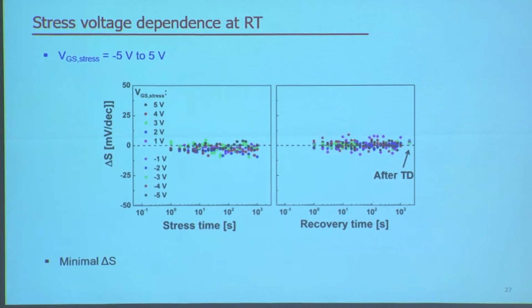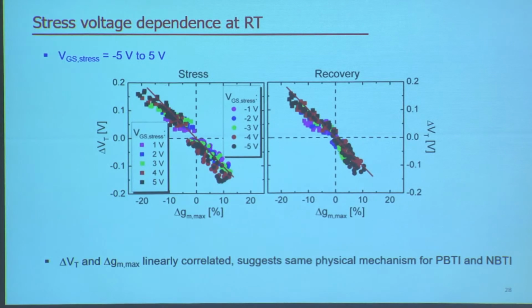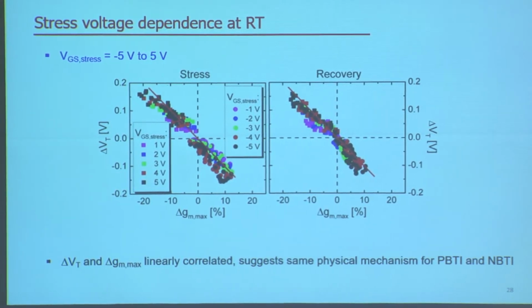So the last parameter we study is the subthreshold swing. And in this stress voltage regime, there is very minimal subthreshold swing change. So as you saw earlier, the main change in this stress regime is the delta VT and delta GM max. So we plot the correlation of the delta VT and delta GM max for both stress and recovery for all the 10 stress voltages. And we observe they are linearly correlated throughout stress and recovery, which indicates that for both PBTI and NBTI, they probably have the same single mechanism that is responsible for the VT shift.